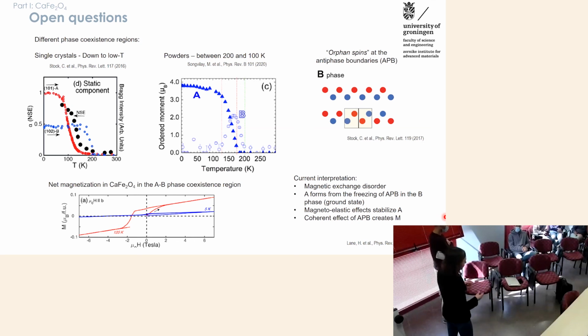And the reason for this is that when we look at our targets after the growth, especially when we grow at lower laser fluence, we have some redeposition of iron, and we have these smaller iron islands on the sample. So what we think is that, especially at lower fluence, we can't ablate iron and calcium at the same rate, and we actually have some iron which is remaining in the target. So overall, the stoichiometry is not exactly the same, and we have this iron deficiency at the interface.